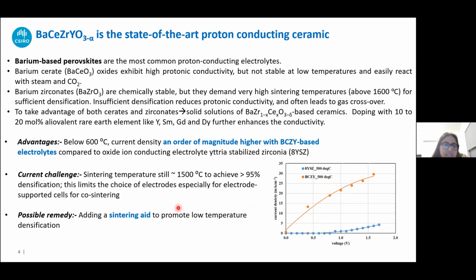However, the current challenge is still the sintering temperature, because even with BCZY, the sintering temperature is as high as 1500 degrees, and this limits the choice of electrodes, especially when we are having electrode supported structures where we are aiming to co-press the materials, like co-press the electrode and the electrolyte and then co-sinter. Then the high temperature limits the choice of catalyst that you can use in the electrode. So one possible remedy is adding a sintering aid to promote low temperature densification.